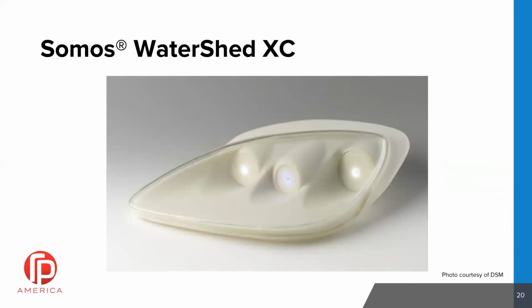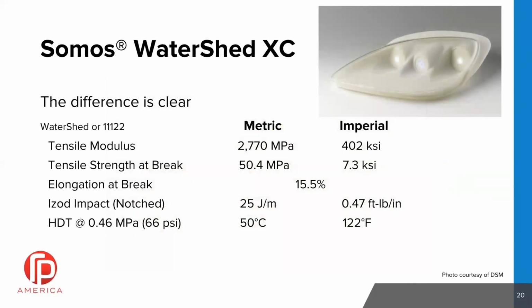Here's another clear example. This is called 11122. The name watershed actually is a little indicative because it means that it repels water. It does not like water. It's really used in casting industries a lot. They'll print materials because in castings, when they're doing the burnout, there's no moisture left over. So it works really well. Good tensile modulus here. You can see about twice as long as on the elongation at break. A little higher temperature in its net state. So just a good all-around material here.